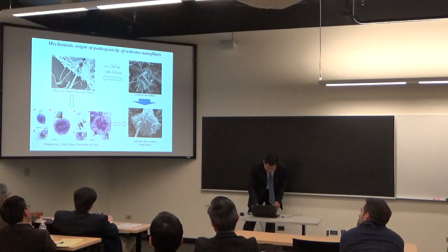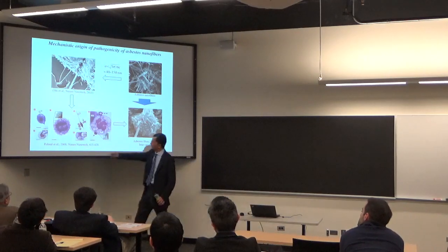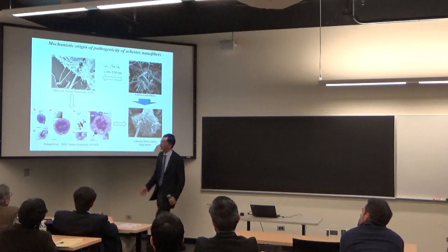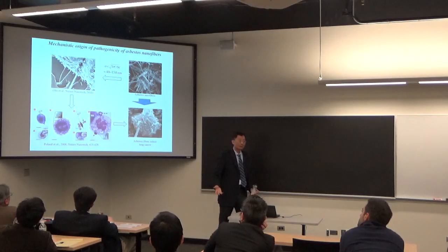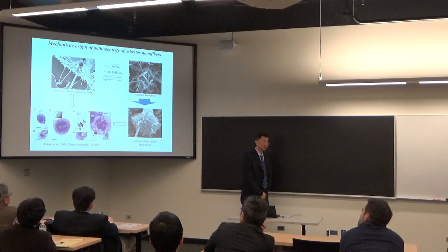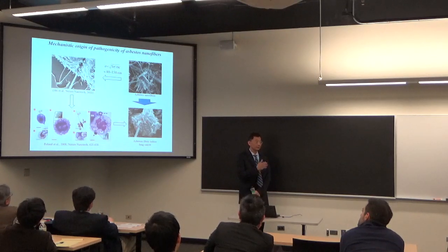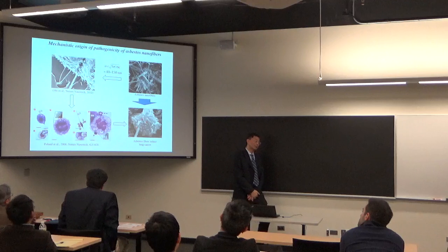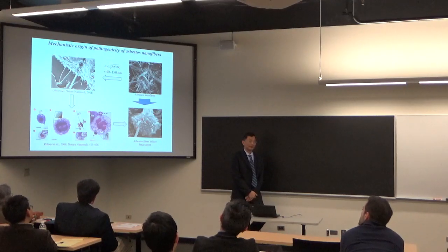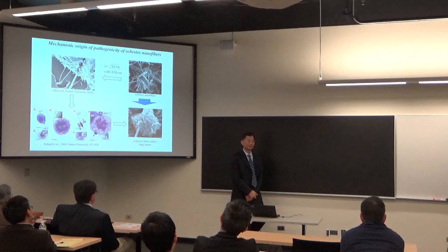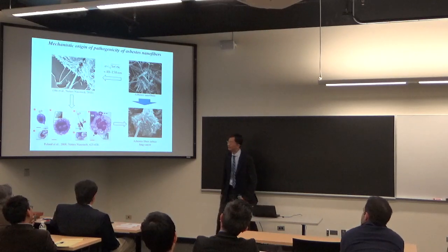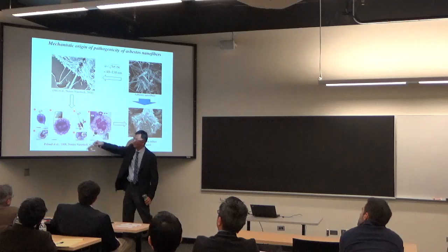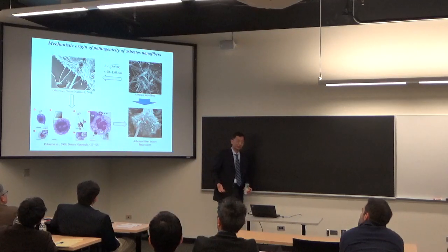What if the fiber is very long? Okay, like in this case, this is a nanotube, but it can be an asbestos fiber too. If the fiber is very long, then the cell really gets confused. Because the task of these cells is to ingest this nanomaterial and then remove it from the human body. But asbestos fibers or common nanotubes, there are a lot of long fibers. They're not short fibers. They're much more for the cell to deal with. So the cell, you can see this picture here, right? The cell becomes stuck on these fibers, and the fiber cannot be easily degraded.